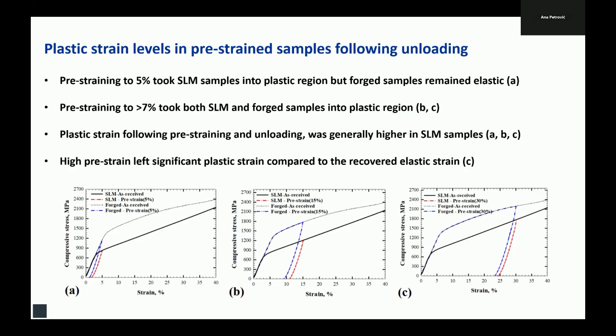To see what level of pre-strain is enough to make an impact on the response, we need to see if we can exceed the yield strength of the material or not. For the 5% for the forged one, we can see that we haven't passed the elastic limit, so we don't expect any impact of that. But for the rest of them, you can see that there is a significant plastic strain remaining in the components, in both forged and the SLM ones, and the same story, very significant plastic deformation when we apply a higher level of pre-strain, which in this case is 30% compared to 15% and 5%.